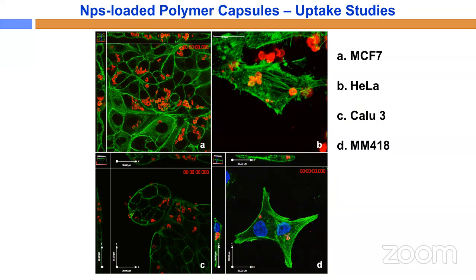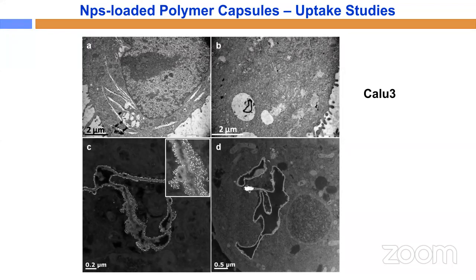But whether the nanoparticles have been released or whether they are still inside the polymer capsule, we have taken the transmission electron microscopy. Here, in order to have a good contrast, we have taken the gold nanoparticle inside the polymer capsules. The bright dots present in the image show that the nanoparticles are still intact with the polymer capsules. So it has not been released.